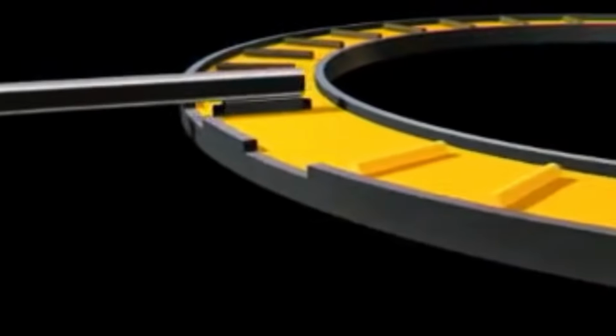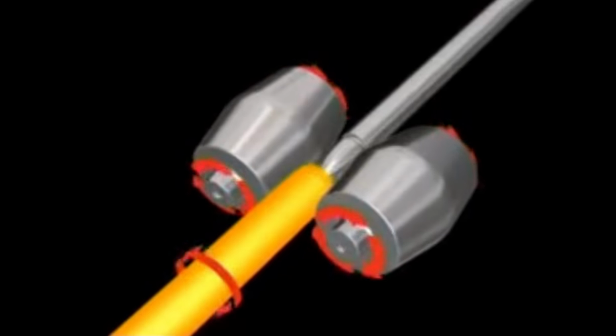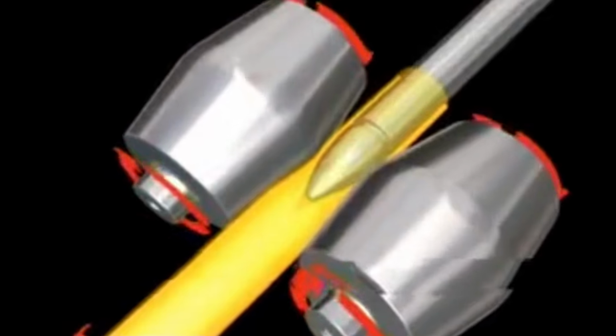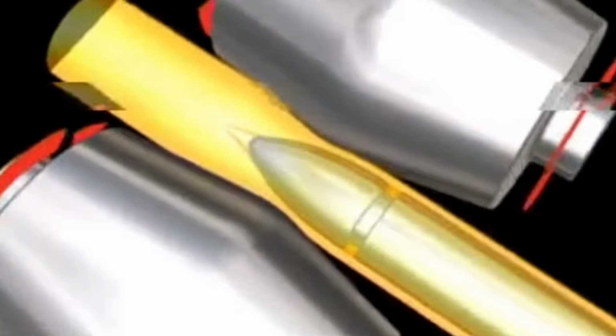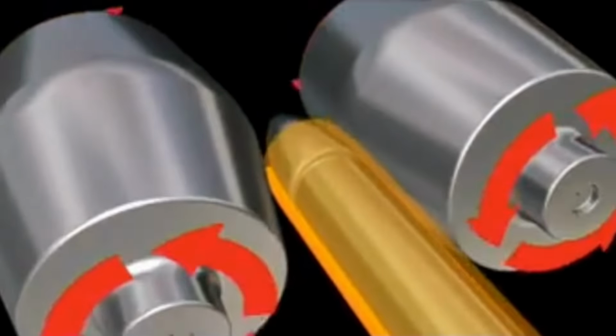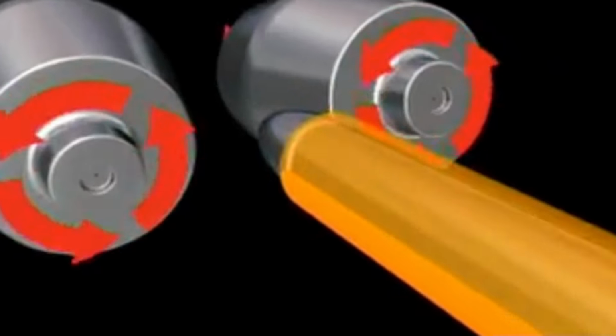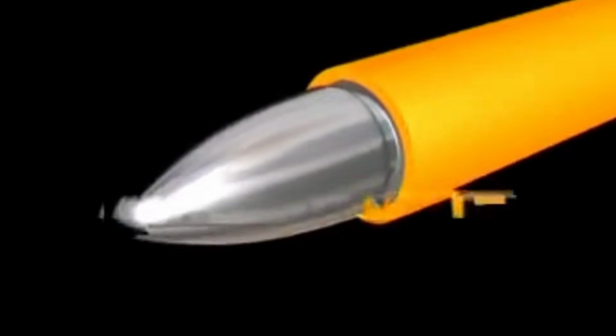Depending on their length and diameter, the heating cycle lasts between 2 and 4 hours, bringing the billets to an exit temperature of approximately 1,250 degrees Celsius. Once the required temperature is achieved, the billets enter the piercing mill for the first stage of hot deformation. Here, they are gripped by 2 skew-mounted conical rolls that force the material forward over a piercing plug, initiating the internal cavity and creating a hollow shell known as the pierced billet.